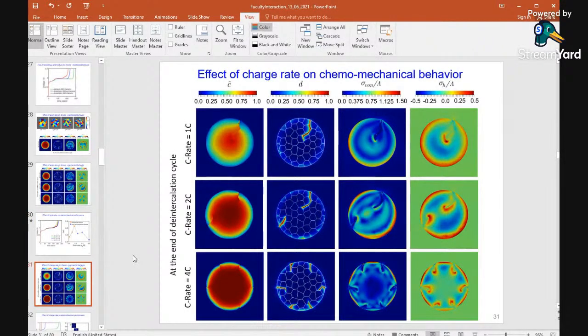So we also investigated the different charge rates and how the crack is developed. In case of a faster charge rate, let's say when the charge rate is 4C, you see multiple cracks are generated, and those again form from the interface. Because in a faster charge rate you deplete very fast at the surface, a high stress gradient is developed, and the stress field is very high at the interface level, so the crack is developed.